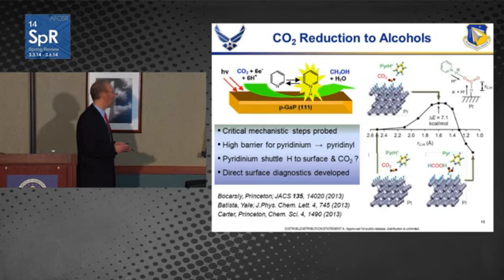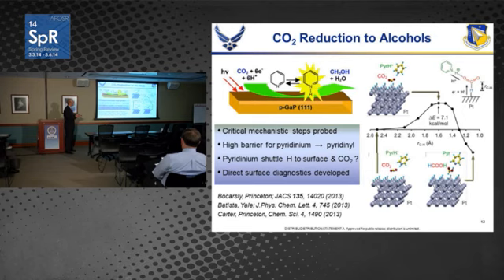And so another group, Victor Batista at Yale, looked at alternative mechanisms. And what Victor has shown is that perhaps the pyridinium is acting as a shuttle, bringing hydrogen atoms down to the surface, and then participating in a proton-coupled electron transfer that can reduce CO2 with a much lower barrier. But again, what's key is what's going on at the surface, at that interface. And again, Tim Lian is part of a team that's going to use sum frequency generation to look at these intermediates on the surface, this real-time probe of these electrochemical processes. So Tim Lian from Emory is going to be looking at that as part of the MURI. Nate Lewis will be using differential electrochemical mass spectrometry, or DEMS, to look at these surface interfaces.